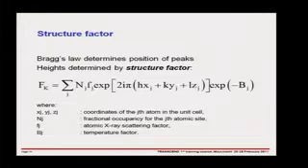The second thing, which is the higher level of sophistication in X-ray diffraction, is we have this thing called the structure factor. Now, you don't need to remember this, but what this basically says is that every single atom in the structure contributes to telling how high that diffraction peak is.